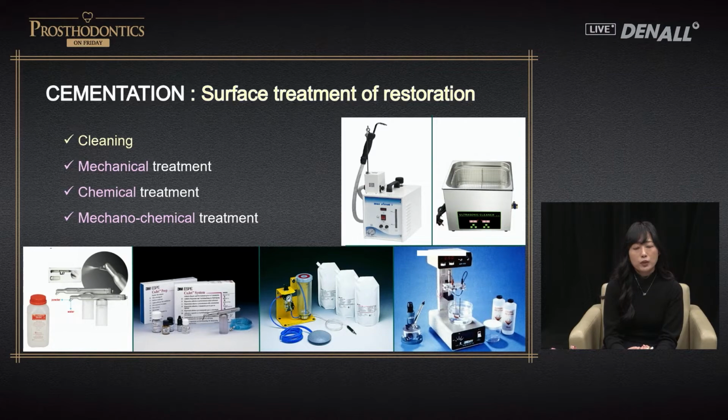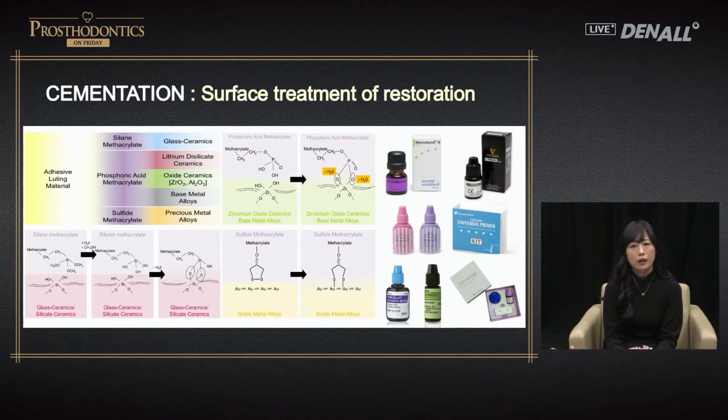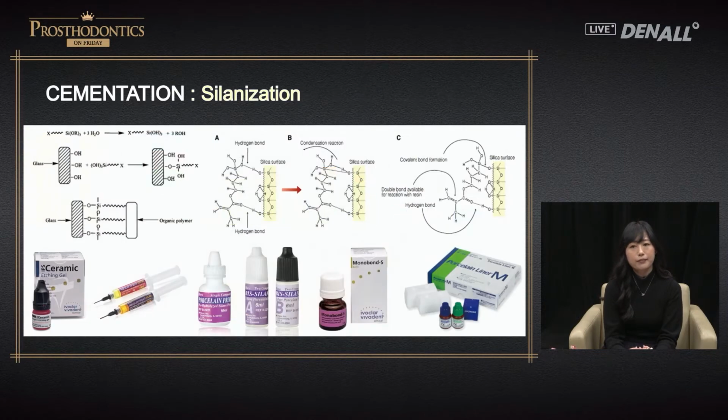Implant abutment should also be subject to surface treatment if necessary. You can use equipment for surface treatment. However, if you don't have it, you can use products available along with the cement. Additionally, in the case of ceramic restoration, for appropriate surface treatment, you need to etch the surface with hydrofluoric acid. Apply silane coupling agent to increase the adhesion between ceramic and resin.